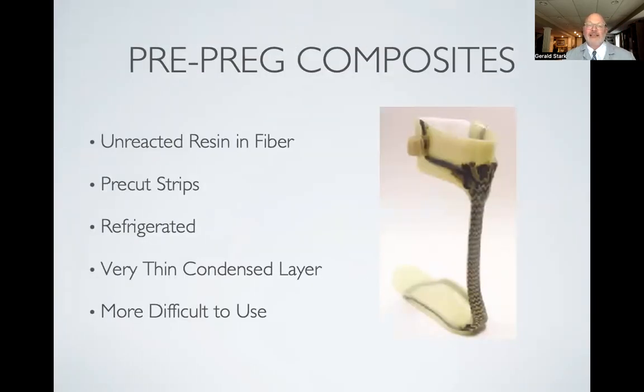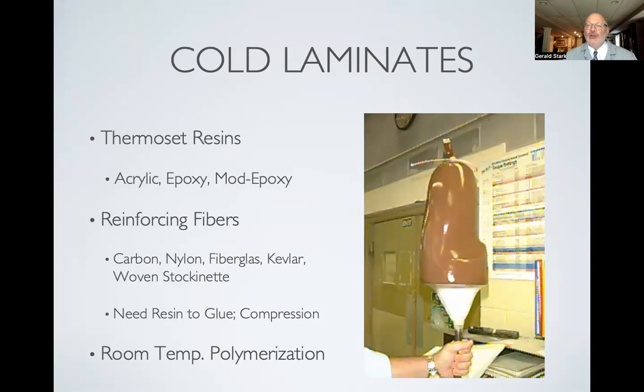So prepreg composites are really pretty interesting because prepreg composites do not have excessive resin. With the previous cold laminates, my friends that are composite engineers used to kind of smile at our use of this. Originally, this was really to create air ducts for planes. Northrop Grumman used to use this, right? They created them out of plaster, and that's what people learned about and applied to prosthetics and orthotics. But it's not a particularly strong structural device. It's strong enough for our use, but it uses an excessive amount of resin.